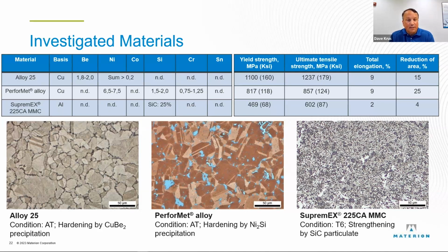And Supremex can't compare to those two, but it is, as I mentioned, 50% stronger than a standard aluminum alloy because of the silicon carbide that goes into it. And then looking at the different matrices, the copper beryllium, the reason it gets so strong is not only does it have hard particles in a soft matrix, which is a strengthening mechanism for all 3 of these materials, but the copper beryllides are coherent with the matrix or the lattice of the copper.